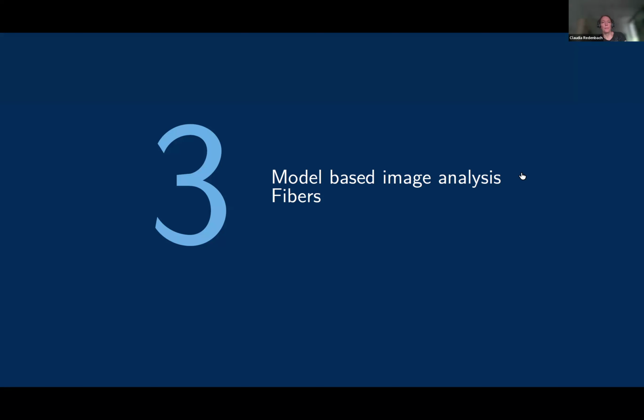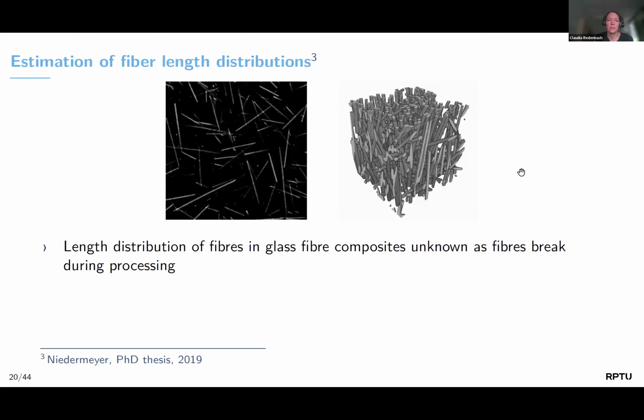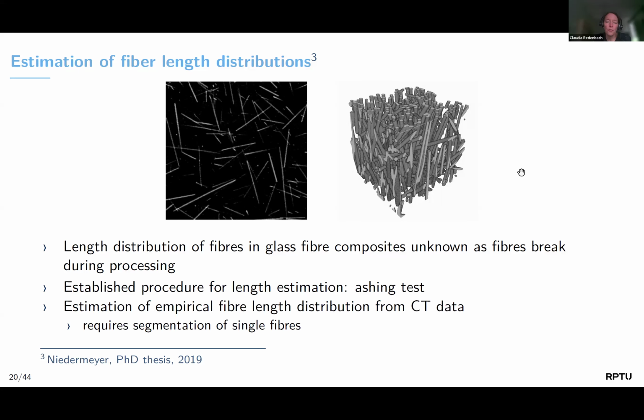As a second application example, I want to show you how to use model assumptions in the analysis of fiber systems, and a particular focus will be an estimation of the length distribution. If you think of glass fiber composites, for instance, it could happen that during processing the different fibers break, meaning that initially you wouldn't know what the length distribution in a composite is. An established procedure for length estimation is an ashing test, meaning you would burn away the polymer. This way, fibers get loose and you could disentangle them and measure their length, for instance, under a microscope. However, also in that process, additional fiber breakage can be introduced.